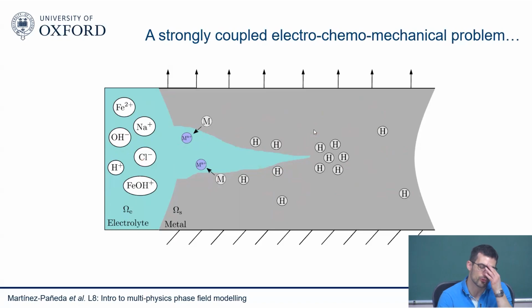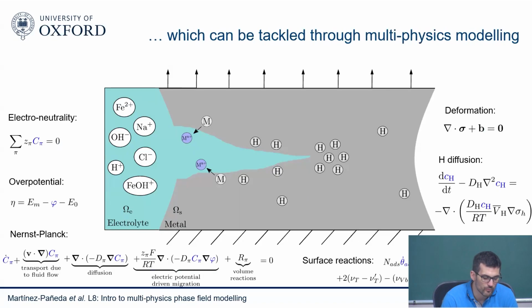This is the problem with corrosion. Many things are happening across disciplines: electrical fields, mechanical fields, chemical fields. And the good thing is that we know the differential equations that describe each of these phenomena. The electrochemical community knows very well how to describe the electrochemistry of electrolytes. As we discussed in the hydrogen seminar here, they use Nernst-Planck, an equation for electroneutrality, or Gauss's law. So here you see the Nernst-Planck equation, for example. You can predict the transport of each of these ionic species, and each of them will be a degree of freedom in your finite element model.